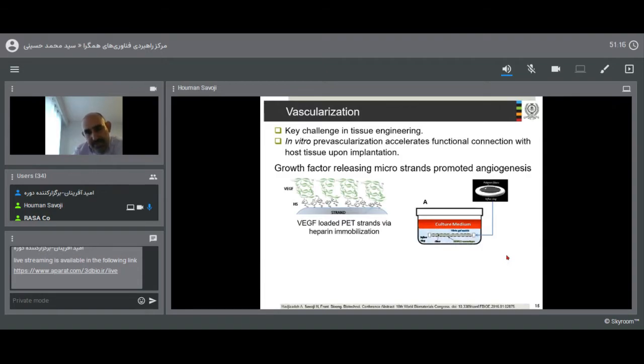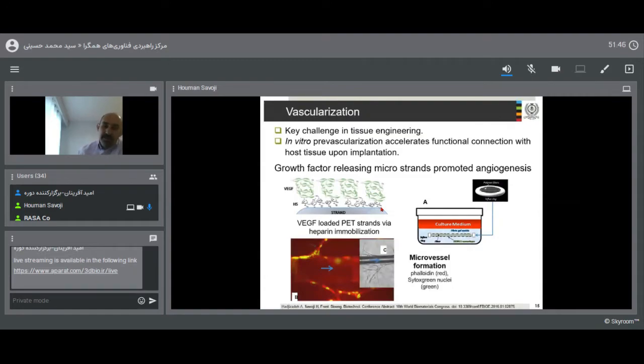To further study this, we developed micro strands, and then we immobilized VEGF, or vascular endothelial growth factor, on top of the heparin sulfate on the scaffolds on the micro strands. Then we wanted to study angiogenesis, or blood vessel formation, in the culture. What we observed is that after being in culture, the endothelial cells started to sprout from the strands and made our tissue vascularized.